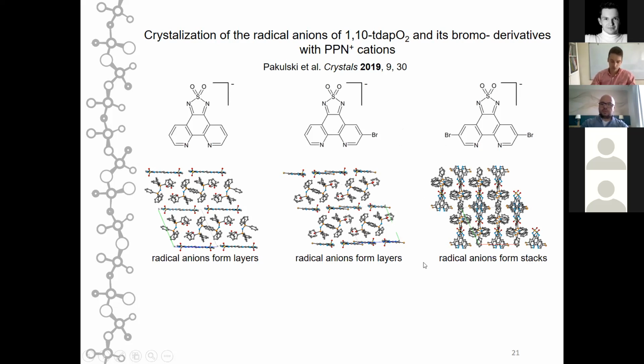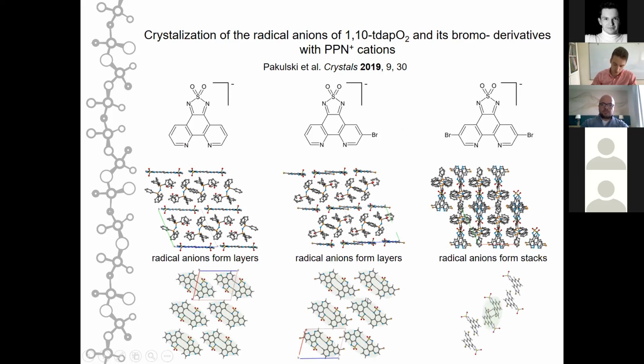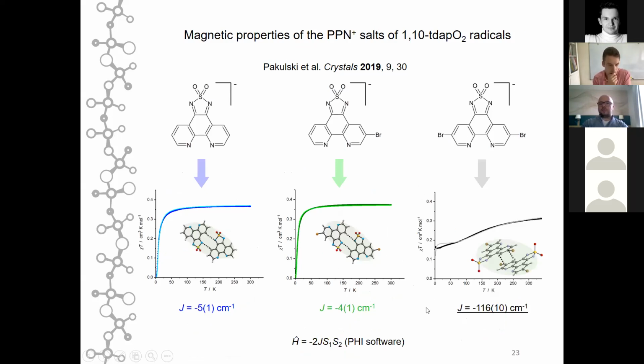It's different for the disubstituted, and this is caused by the disruption of the CH-N hydrogen bond donor and accepting capabilities of the molecule. So when the bromine atoms appear on the 3 and 8 positions, this kind of interaction can no longer occur, and this is why the structure of the compound changes, and the pi-pi stack interactions overcome and control the packing diagram. And this also leads to completely different magnetic properties in the case of the stacked compound.